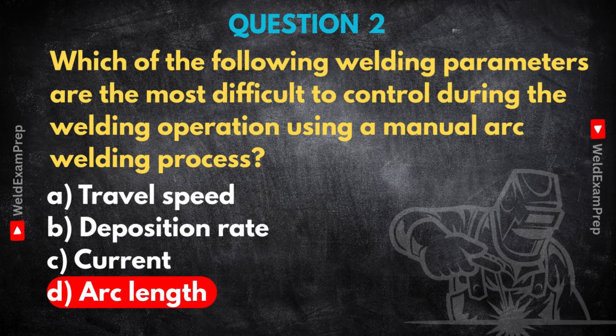I see. It's constantly changing because the electrode is changing. Exactly. And if that arc length varies, it messes everything up. Too long an arc, the voltage jumps around, you get more spatter, less penetration, maybe a wide, flat bead. Too short, you risk sticking the electrode or stubbing out, which can cause lack of fusion or other defects. It's a real balancing act. It sounds incredibly difficult to maintain perfectly, like trying to draw a straight line while your pencil keeps shrinking. That's a great analogy. It really is.